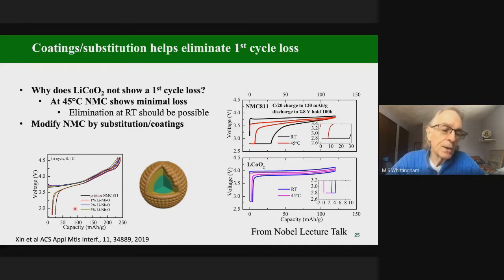And you can see doing this, we've now reduced our first cycle loss by about 40%. So we feel by doing this with better materials, we can eliminate the first cycle loss altogether. And you can see this doesn't matter whether it's 1%, 2%, or 3%. It has the same effect. So a very small amount of substitution will modify it.